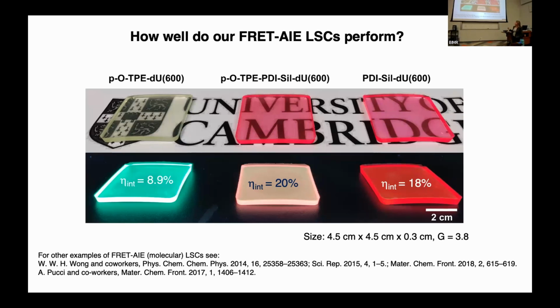And what we can see is that when we just have the donor, our internal efficiency is about 9%. When we just have the acceptor, it's about 18%. But when we combine the two, we get a small increase of 2%. So it's 20% in total. That's a reasonable increase in terms of LSC efficiency. So we were quite happy with that.